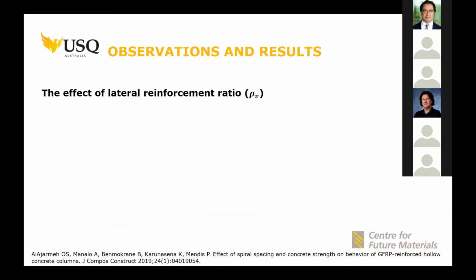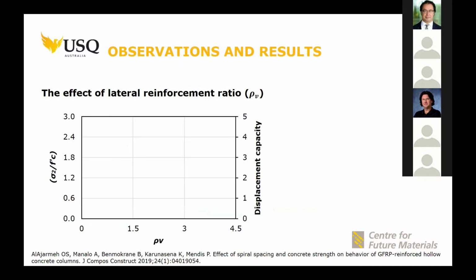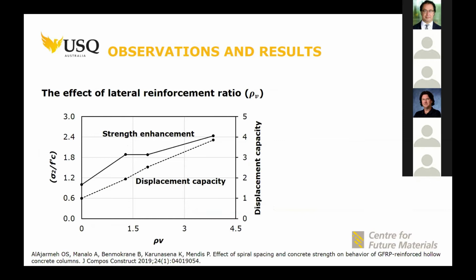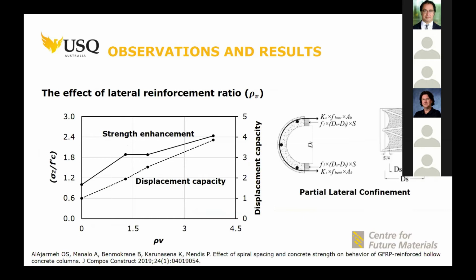For the effect of lateral reinforcement, we changed the spacing between the lateral reinforcement and, as expected, we got a strength enhancement in the core and also a significant displacement capacity, and that was related to the lateral confinement concept from the bars and from the spirals.